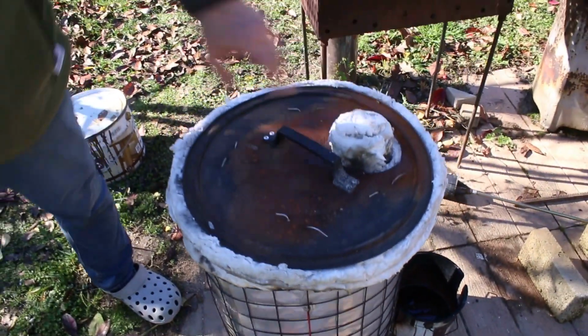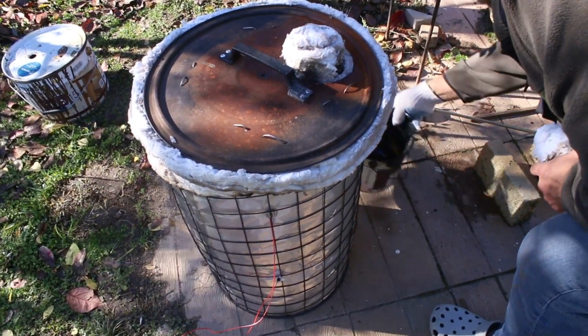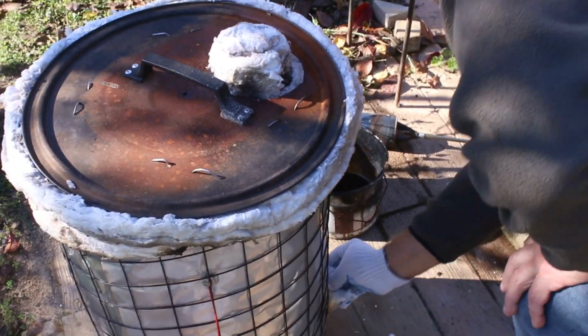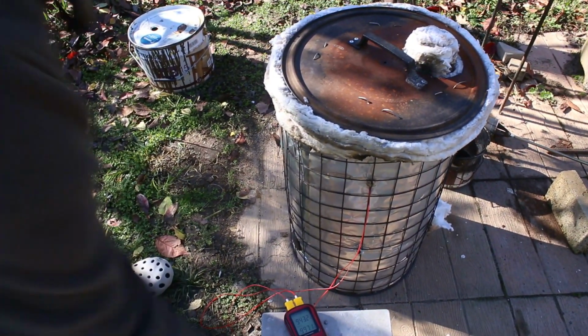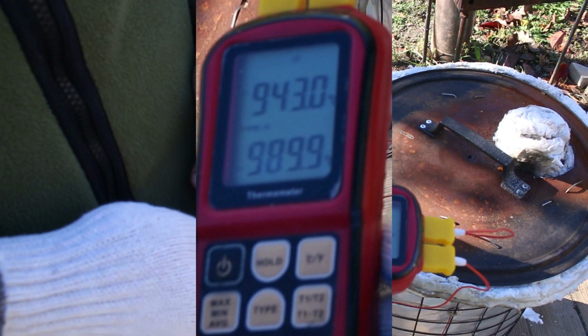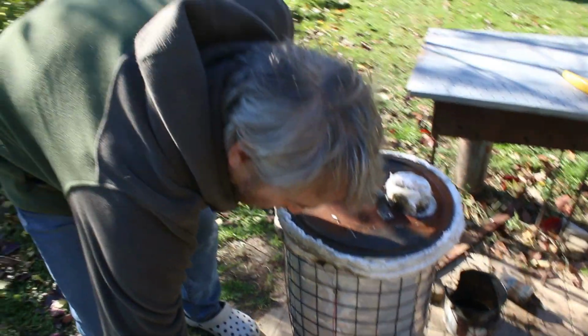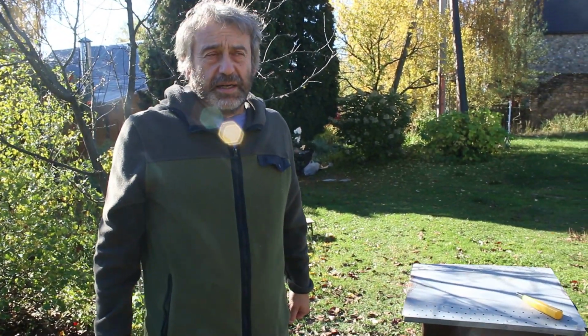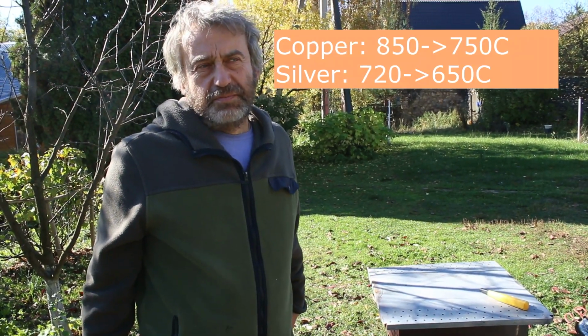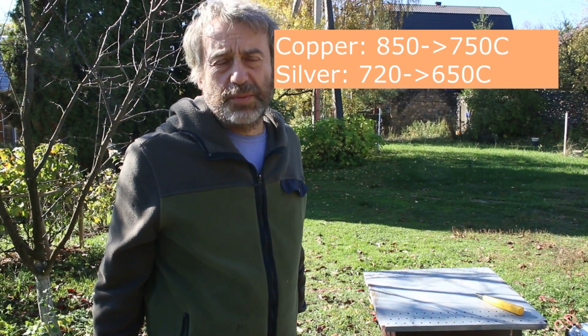So now we close both the hole entrance for fire and the damper, and look at the readings of the thermocouple. So we see the temperature dropped quickly, and then the difference between readings shrinks to about 50 degrees, which is a normal distribution for this very small tiny lustre kiln. So now let's wait 15-20 minutes. The inertia is very low, and we are interested in the reduction window around 700 degrees. We have mostly silver lustres, so it's a 650, 720 reduction window, and so let's wait a couple of minutes. But we have to be around not to miss the window.